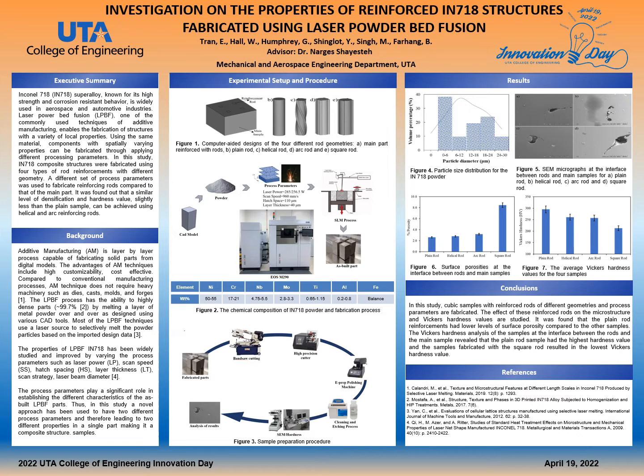The composition of the as-obtained powder was determined using energy dispersive X-ray spectroscopy, or EDS analysis, as shown in figure 2. The analysis of the SEM micrograph of the fresh powder revealed the average powder particle size to be around 12 microns. Microstructure analysis of the as-built samples was conducted in order to study the cohesive behavior between the main sample and reinforced rod.